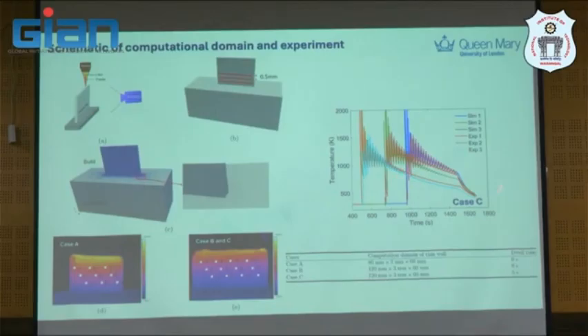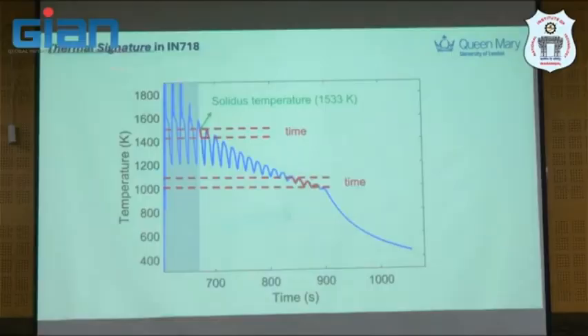And this is the model that you can see, simulation versus experiment. You see there is some mismatch in case C, but it still captures the trend of the thermal cycle. Why is this important? Because the thermal signature here is something like this. You have some time between solidus and liquidus temperature. It's a characteristic of additive manufacturing that there is no smooth curve like that, but this is what happens in real life. This is the complicated thermal signature, as I said. And then you can count that before it actually solidifies,